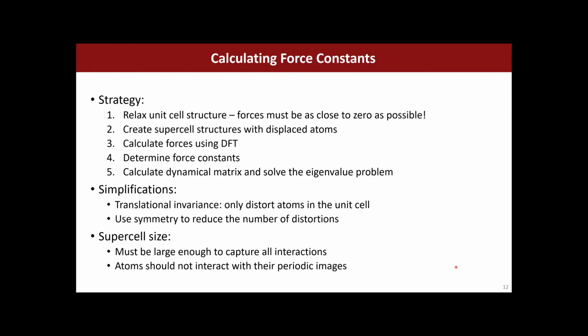We can make a few simplifications here. Technically, we need to displace every single atom in the entire crystal, and then we can get a good measure of what the force constants are, but that's not necessary because we have translational invariance in the crystal. If we displace an atom in one cell, or if we displace an atom somewhere in another supercell, it doesn't matter. It should have the same impact. So we can already just focus on the unit cell, which is good.